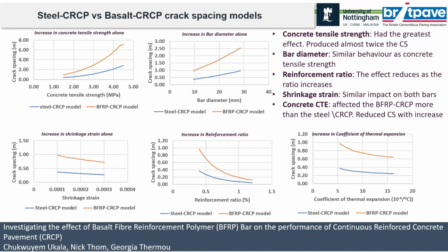That was very clear. If only the concrete tensile strength was used, it showed us a double from the beginning to the end. So irrespective of how we increased the tensile strength of the concrete, we always had double the crack spacing. But we also noticed that the difference also repeated itself here in the bar. And we noticed that for the reinforcement ratio, as we kept increasing it, the effect of the reinforcement ratio of both steel and bars was diminishing.